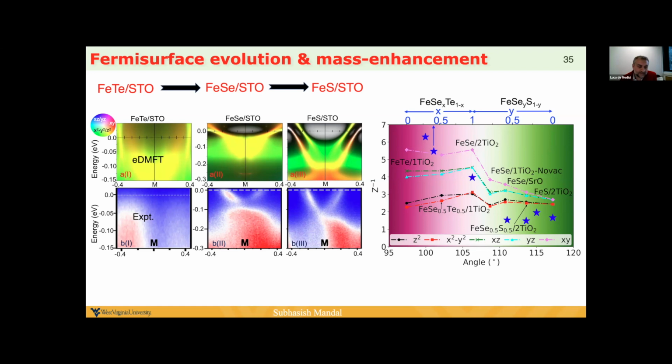Okay, thanks. Subhasish, let me ask you a trivial question. Why is your perfect magic angle 107? Naively, I would say it should be 109, like the perfect tetrahedron. Yeah, this is the cost of going from bulk to an STO heterostructure. The lattice parameter here is actually the STO lattice parameter that we used, which is seen in the experiment.